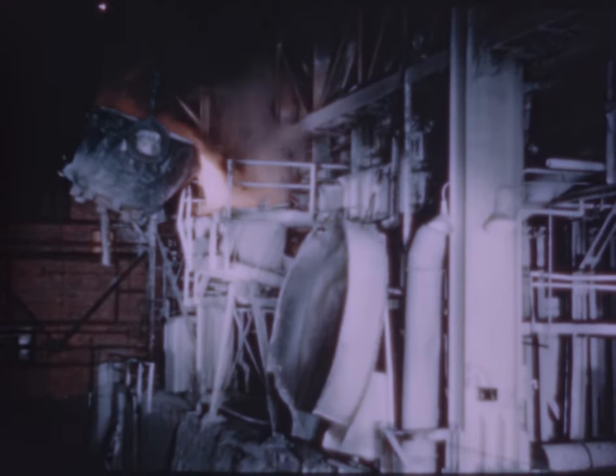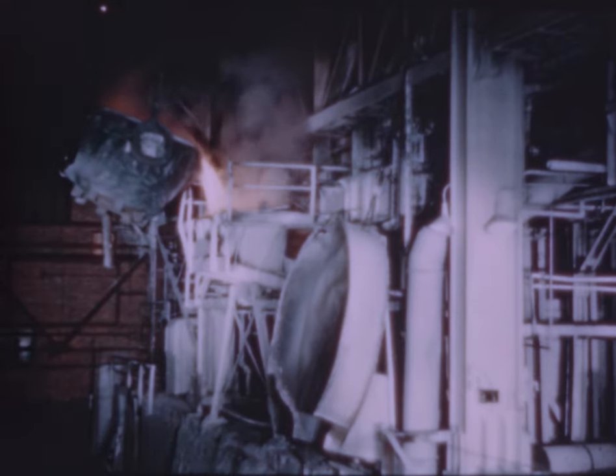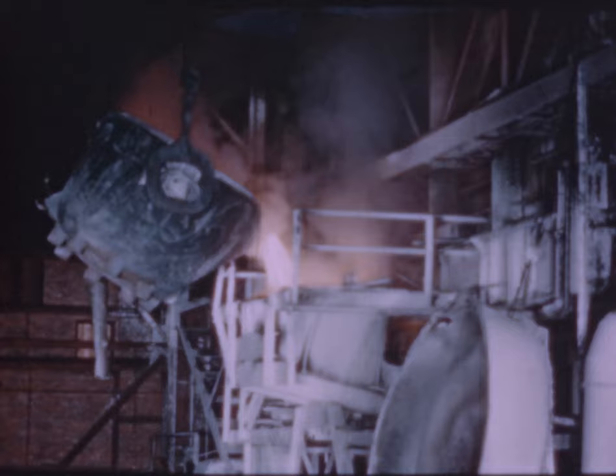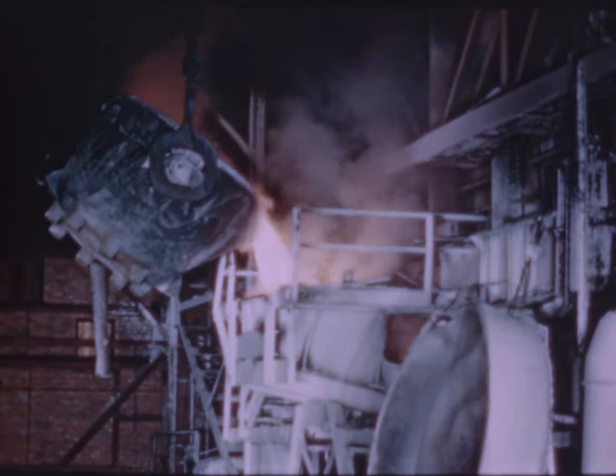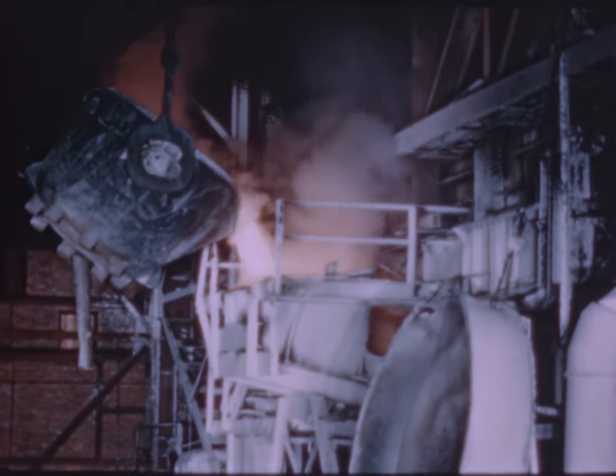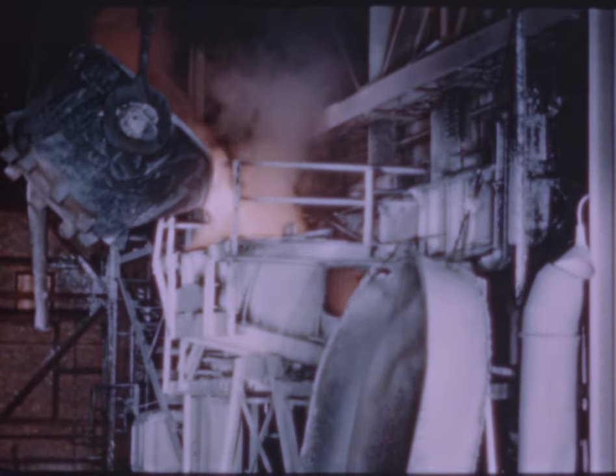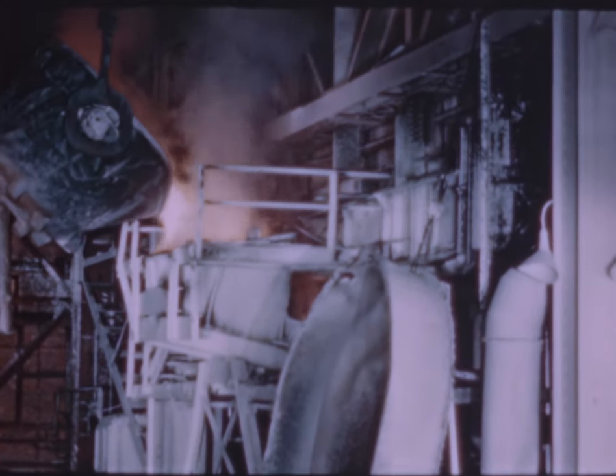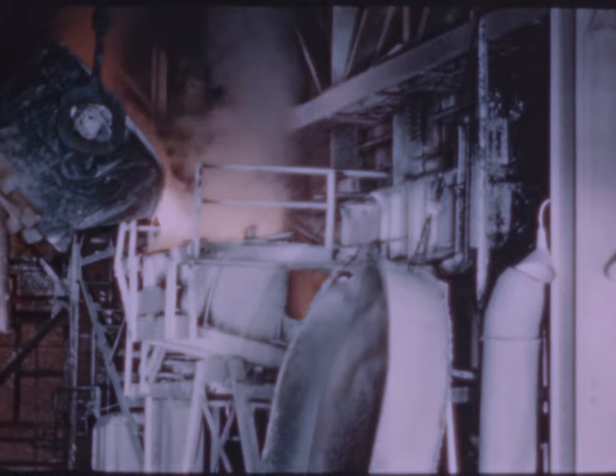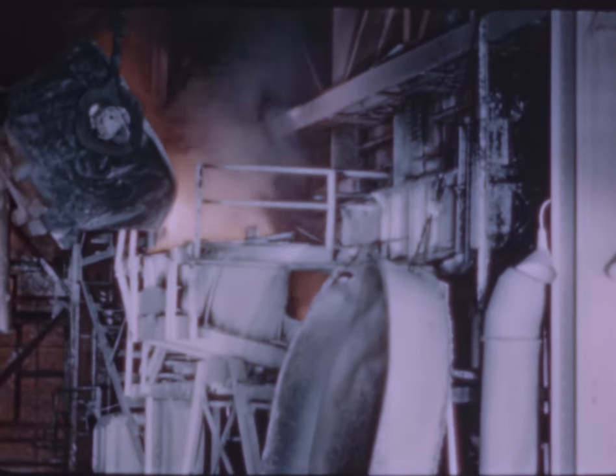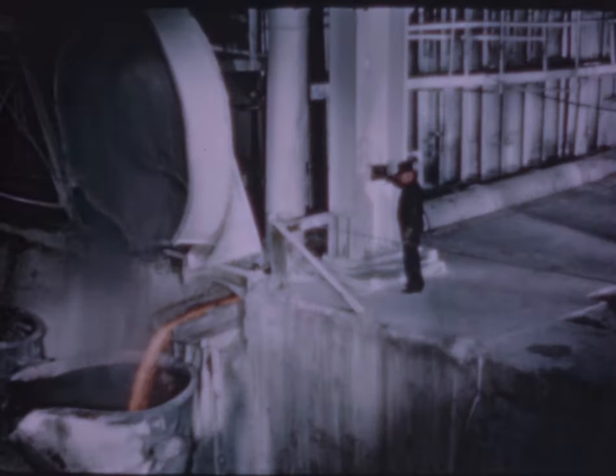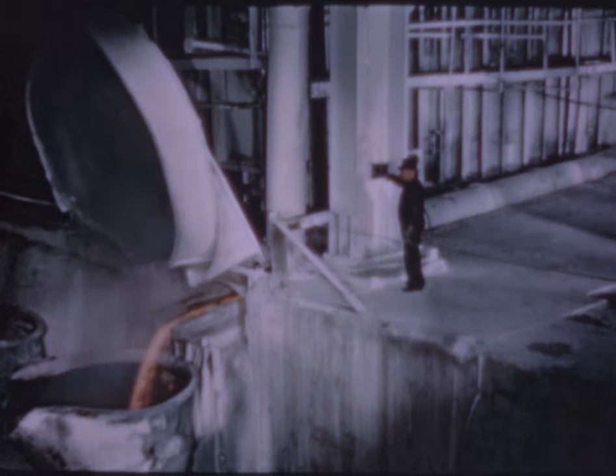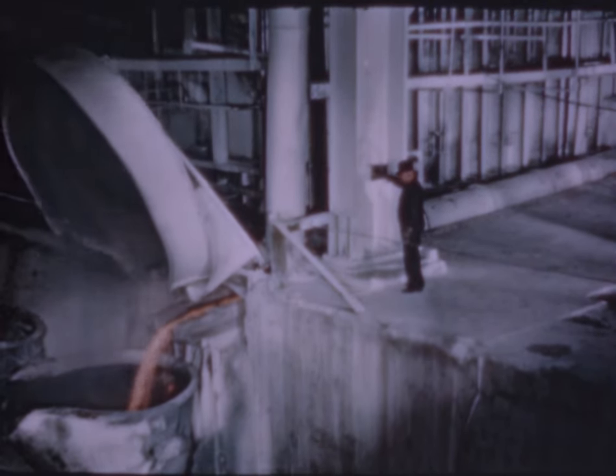Reverberatory furnaces are huge gas-fired brick-lined structures taking several hundred tons at a charge and permitting a continuous smelting operation. The hot calcine is dropped at intervals into the furnace from the charge floor above. Fluxes are added, and so is some of the converter slag. At a temperature of about 2600 degrees Fahrenheit, the charge melts and separates by gravity.